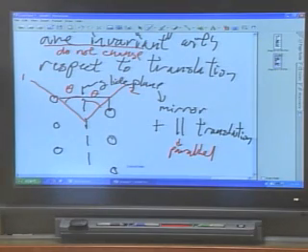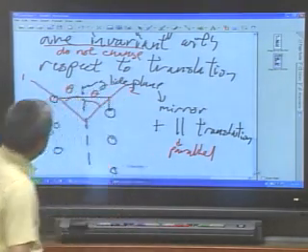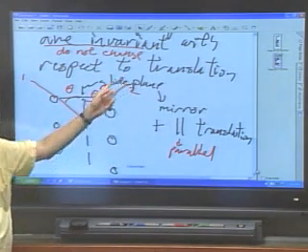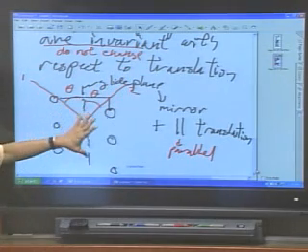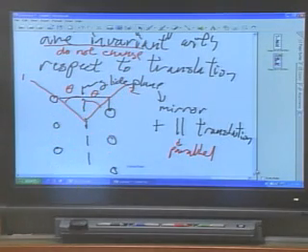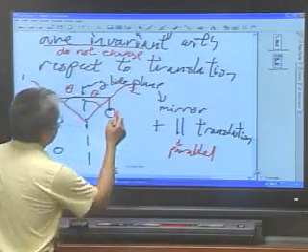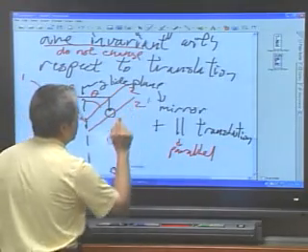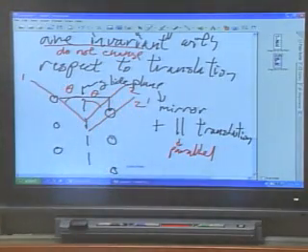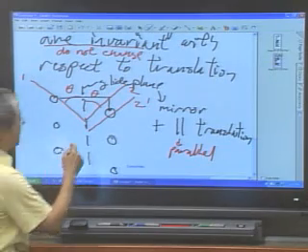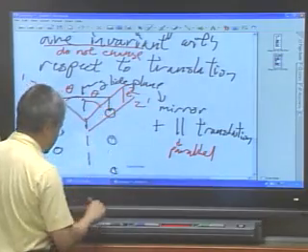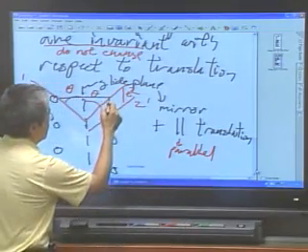You say, well, not really, because you take the atom, and the atom coming in the 1 direction is going to see one environment. The atom coming in the 2 direction is not going to see the same environment because all these atoms are shifted down a bit. Okay. Well, that's fine. All we have to do is define a 2', where the 2' is in this direction here. So the only difference between 2 and 2' is I moved it down a bit. And this distance here is some distance t, which is the same distance as we translated, this distance here, t.